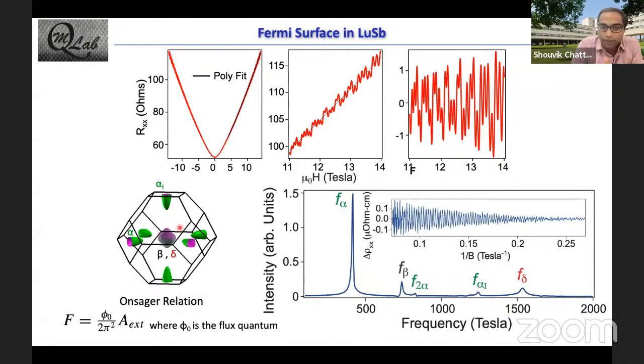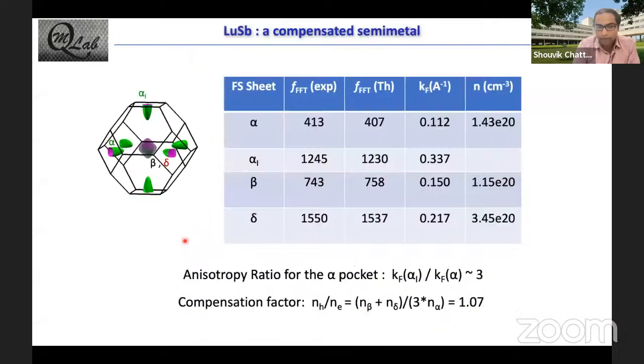This is from density functional theory calculations. What you see here at the center, we have 2 hole-like pockets. And at the zone edges, you have an elliptical electron-like pocket. And when we analyze our data from the Shubnikov-de Haas oscillations, we get both the components from the electron-like pocket and the hole-like pocket.